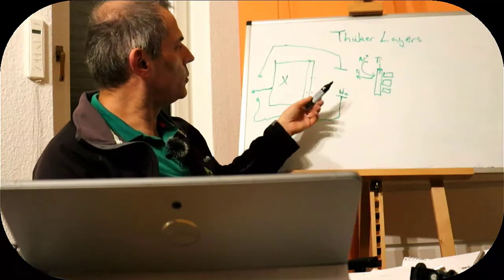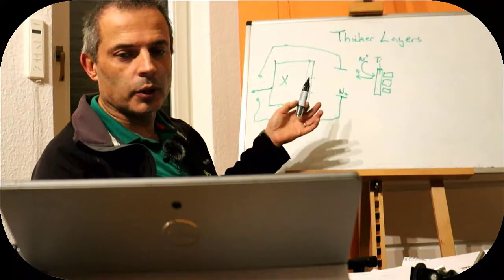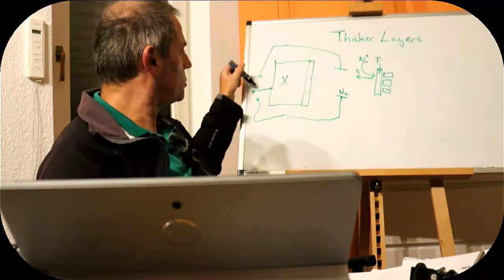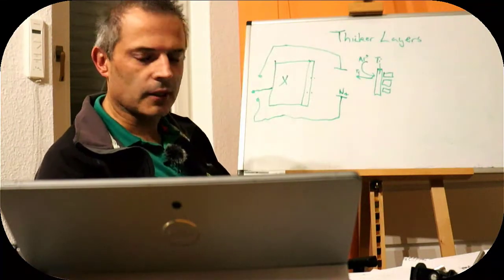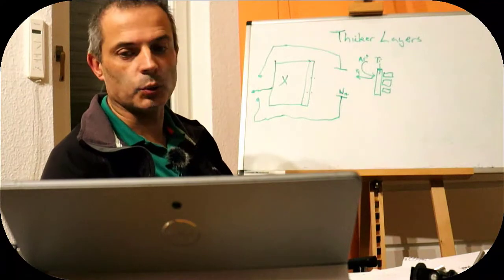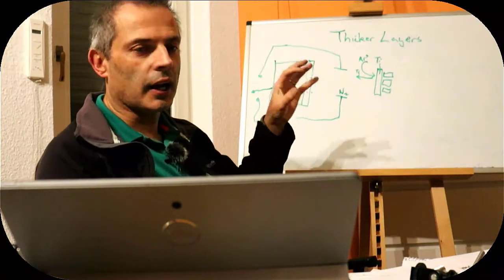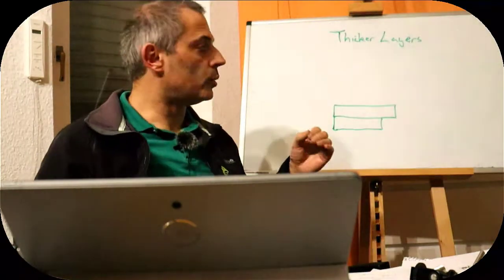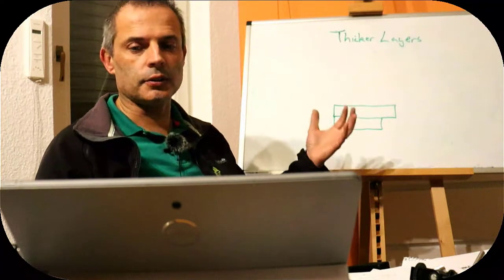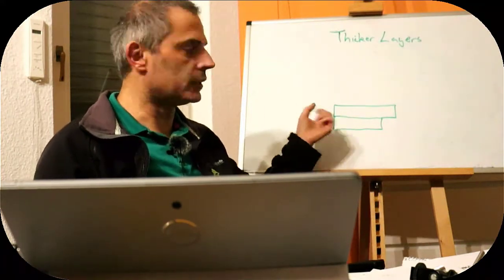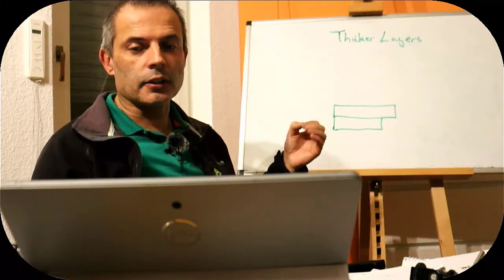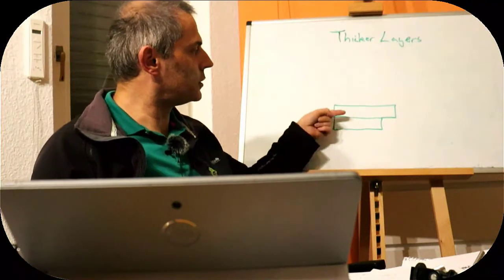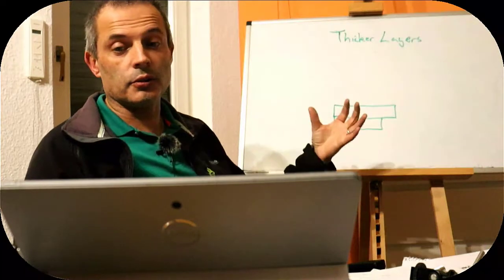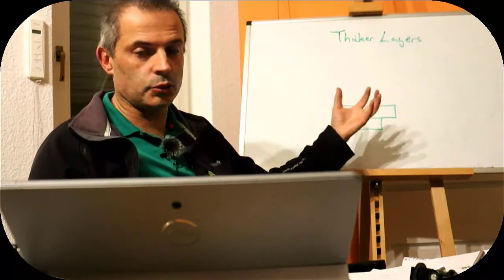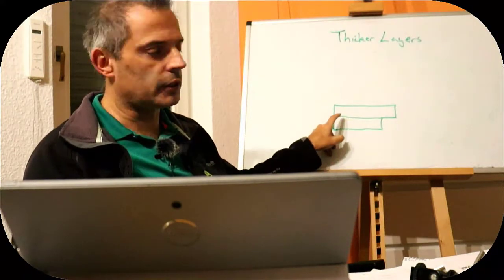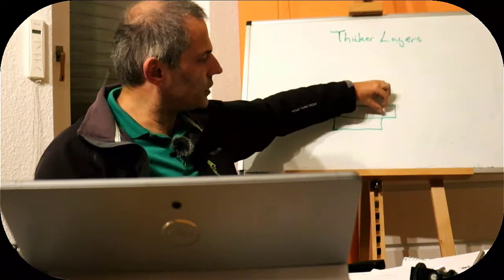The ions generated, we can accelerate towards our substrate by either their self-charge, but that's not very efficient and not very easily controllable, or we can control the voltage from behind. So that would make it a little bit simpler setup, but it's not quite as obvious to look at, and it's not as controllable. The problem with generating compressive stress is that although it does protect our coating from breaking due to scratching, it can't sustain a very high thickness, because as we increase the thickness of our stressed film, we're increasing the force, and we're not changing the thickness of the interface or the strength of the interface.